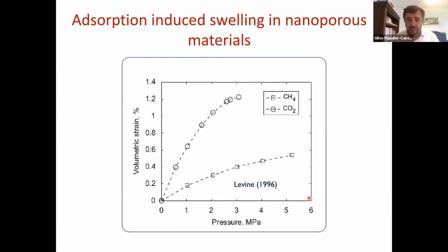If you take a piece of porous material, saturate it with a fluid or a gas, and increase the pressure, instead of shrinking, it swells. This has been measured quite a long time ago - here you see results from Levine in 1996, measuring the swelling as a function of the pressure in the fluid.